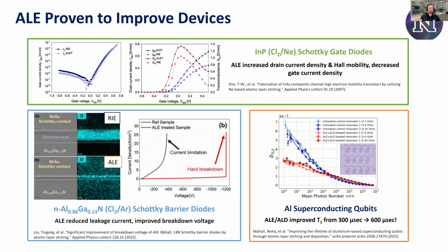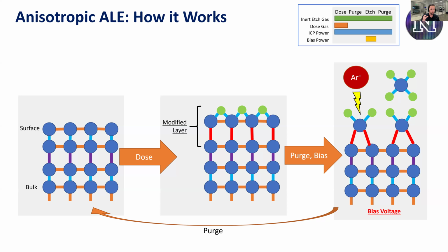So say you have silicon, you chlorinate that surface. You form silicon-chlorine complexes at the surface. There is not enough chemical energy to create a volatile product just yet. So then you remove excess chlorine from the gas phase, and then you go ahead and use a little bit of argon with a bias, and you remove those surface complexes. These are cartoons. This is not molecular dynamics simulations. Then you purge it and go again.